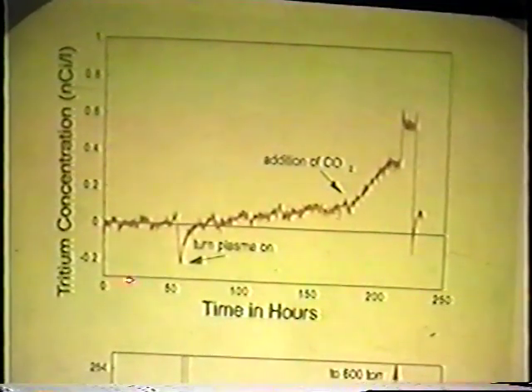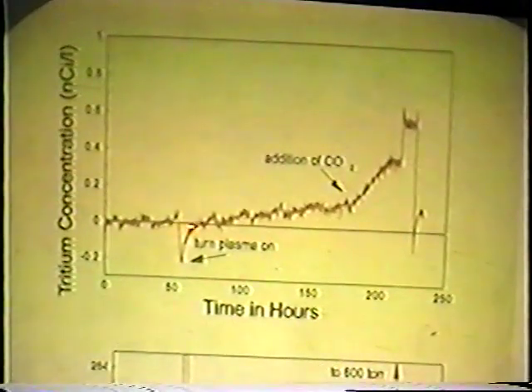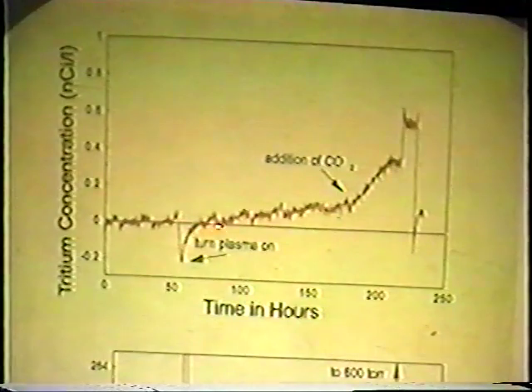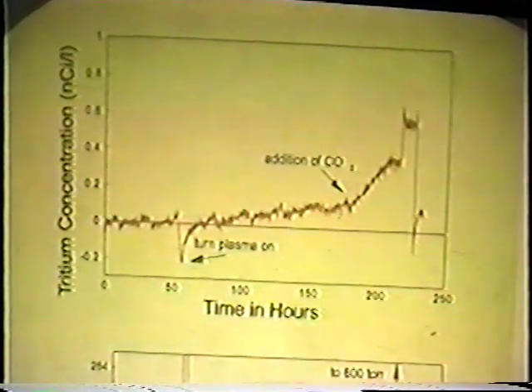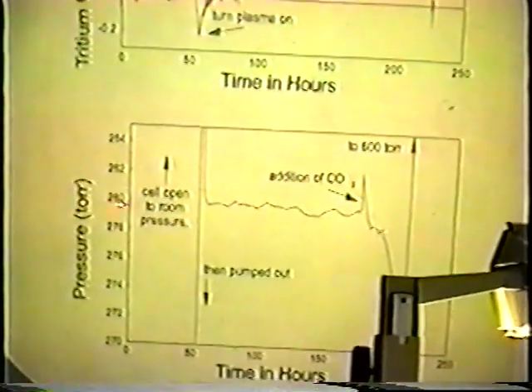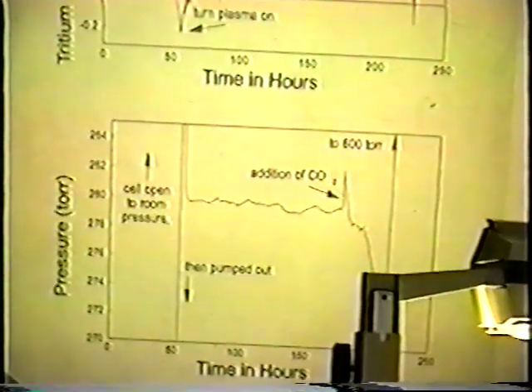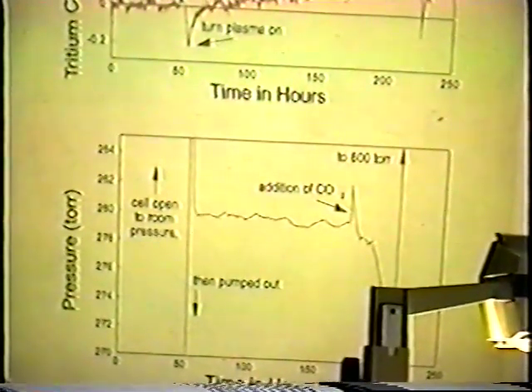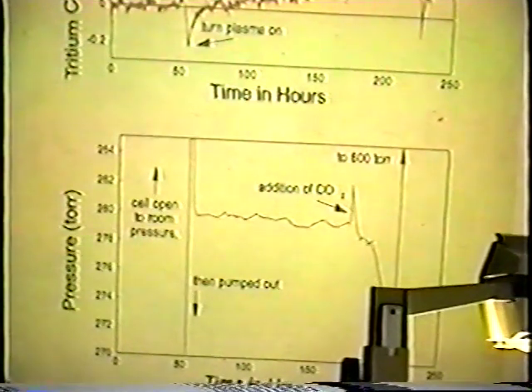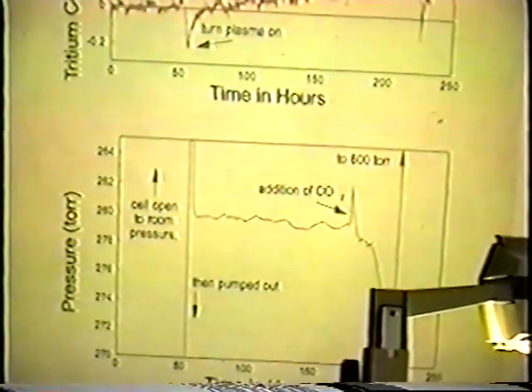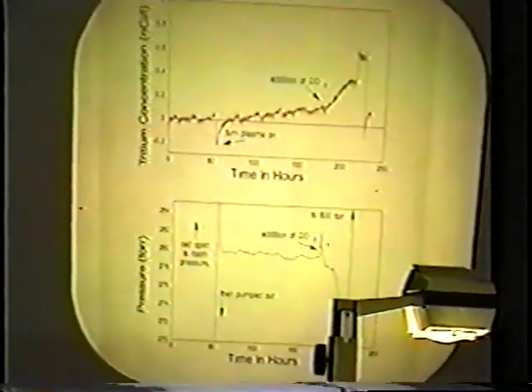And this is a plasma cell from a particular material. You turn it on, it's a very weak producer, nothing much happening here, until we add 2 torr of CO2 and 280 torr total in the system, so it's a very small percentage. And what has happened is that the tritium output has gone up by about a factor of 5 here. And also the pressure has dropped. Now the pressure will drop down as this is converted to water to 278 torr.